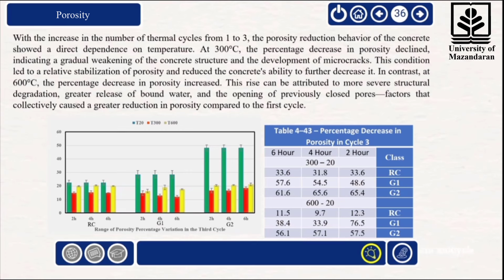At 300 degrees Celsius, porosity reduction decreased, reflecting the gradual weakening of the concrete structure and the propagation of microcracks, leading to relative stabilization of porosity and reduced capacity for further decline. In contrast, at 600 degrees Celsius, porosity reduction increased, likely due to more severe structural degradation, greater release of bound water, and reopening of previously sealed pores, all of which contributed to greater porosity loss compared to the first cycle.